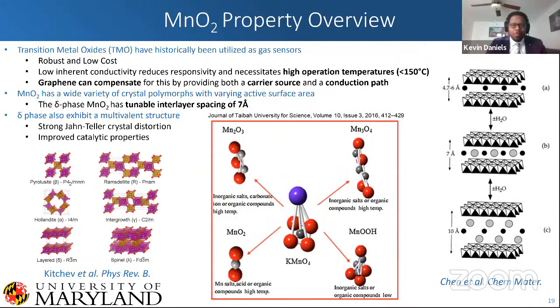So just an overview of the transition metal oxides, going towards manganese dioxide. They have historically been used as gas sensors. They were actually the first gas sensor introduced in the 60s. The issue behind these sensors is in order for them to have any remote detection capabilities, they have to be heated up. So they have relatively low conductivity and responsivity, and you have to operate them above 150 C. I don't know, y'all, but I'm kind of leery about having an oven sitting on the wall just to detect things like smoke, for instance.